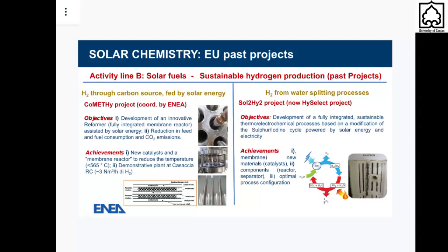And in the project, materials like catalysts and components like membrane reactor were developed to reduce the operating temperature from 800 degrees C, 850 degrees C, which is the conventional temperature for reforming of methane, to about 550 degrees C. And the pilot plant was built connected to a molten salt circuit, which powered the endothermic reaction.